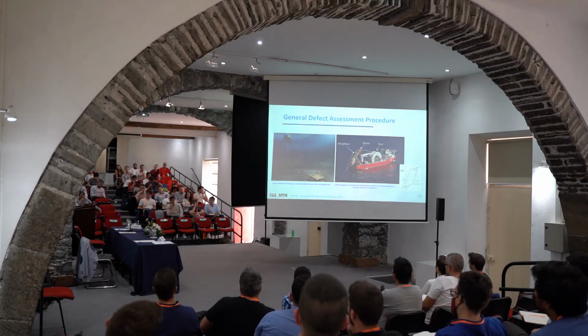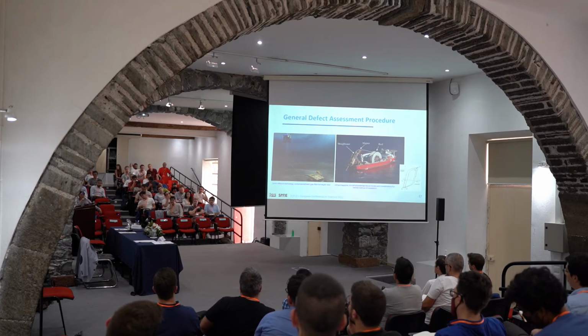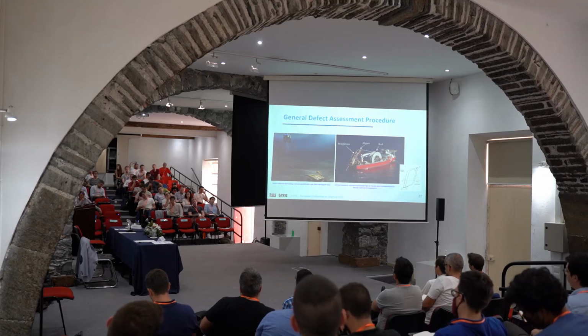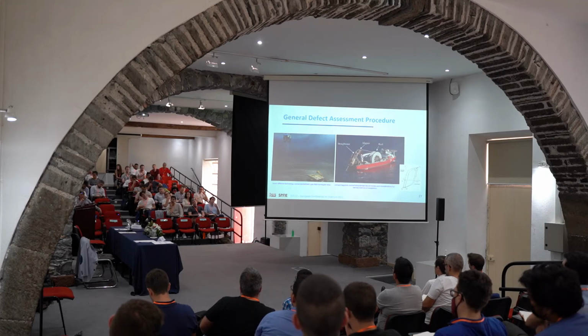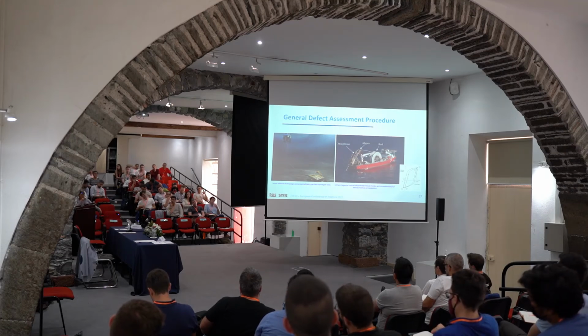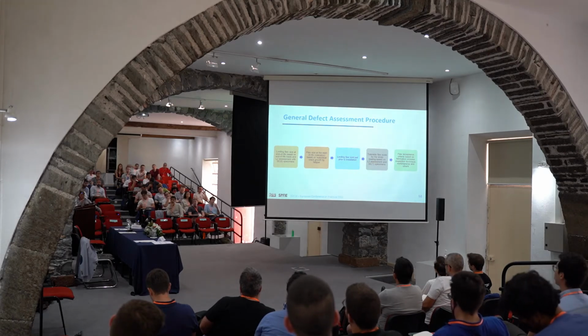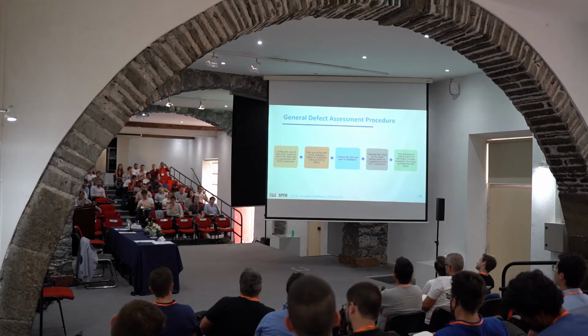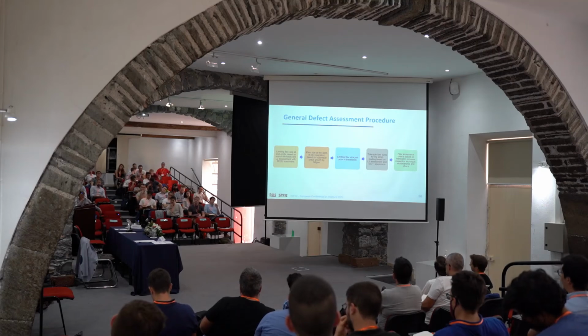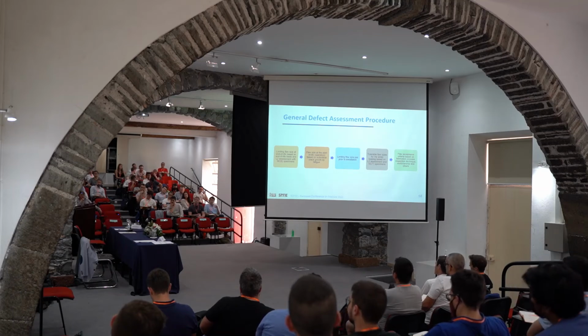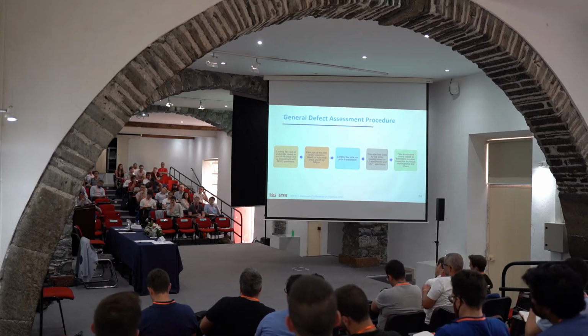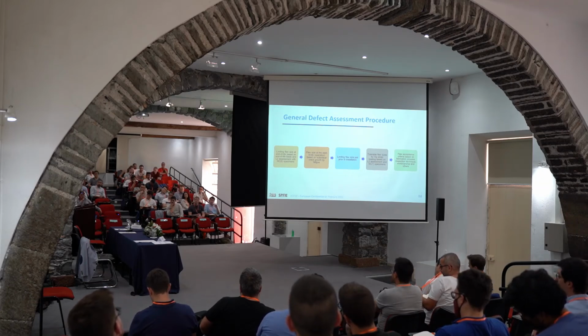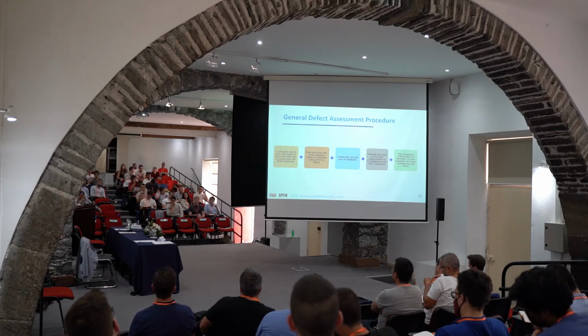But don't be fooled by the picture. There are lots of loads on the seabed. The current, the soil is moving, and also you have some fatigue loading. Not high loading on the seabed, nevertheless, some fatigue loading. So you need to be sure that after 20 years, your installation is safe. Say, to be safe, the maximum crack size is 7 millimeters. Then I ask, what's all the damage that can occur during the 20 years? I say 2 millimeters. So I subtract, and when I install my pipe, the maximum crack must be 5 millimeters.